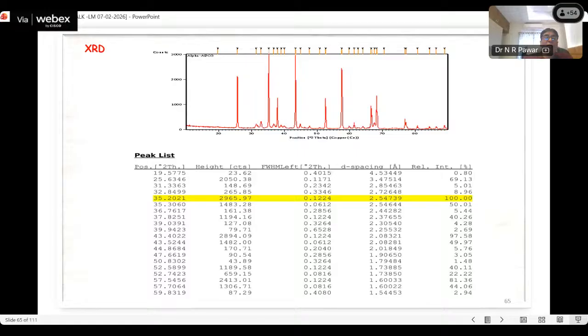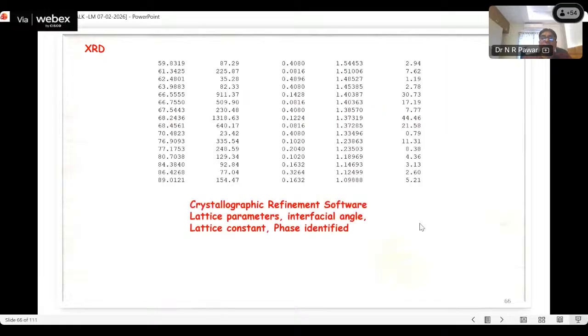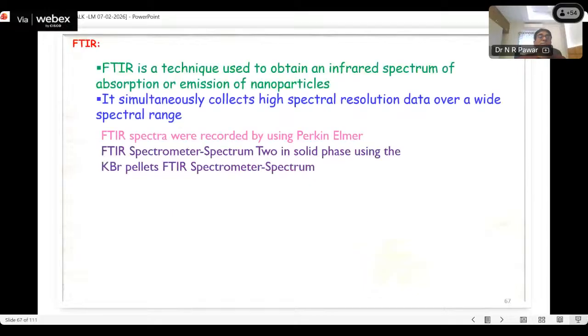And now these parameters or values go into crystallographic refinement software. There is one software, the crystallographic refinement software, and by putting these values in that software, we obtain the lattice parameter, interfacial angle, lattice constant, and the phase identified by using this software, by considering the maximum peak of the XRD pattern and the related value.